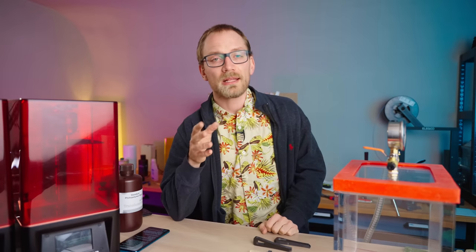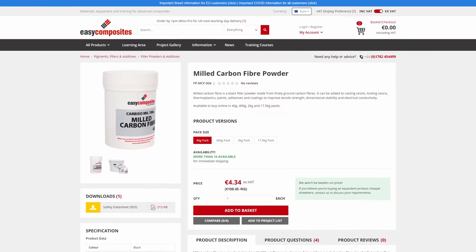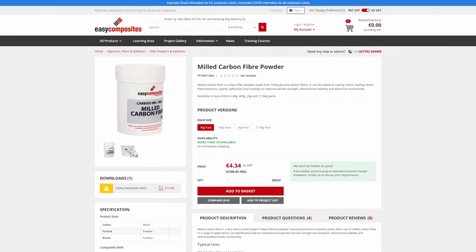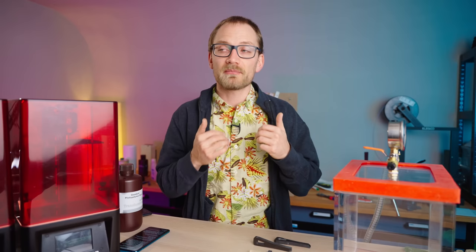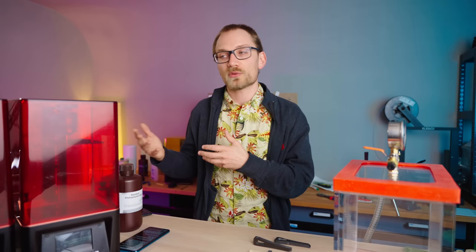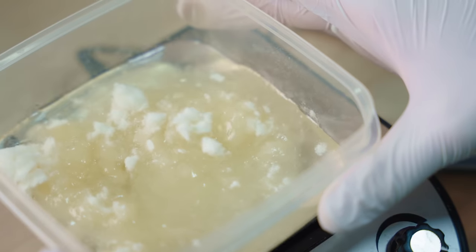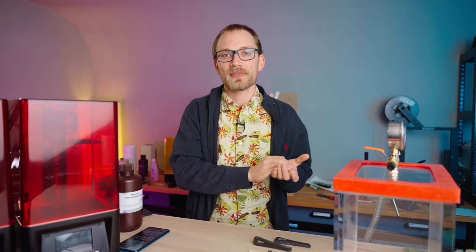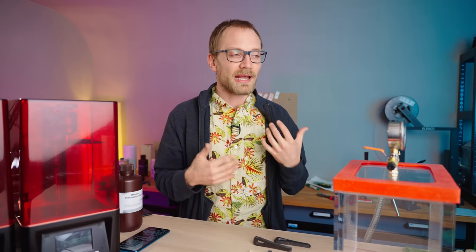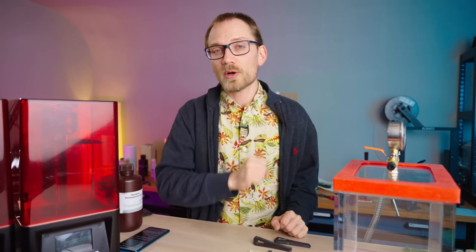In this case, I think there's also just not enough of the chopped fiber in the material to give an even improvement in strength, and if I would add more, it would not be very printable anymore. So what we're seeing is that there's just blotches of very strong and rigid bits in the material where there's the fiber added in, and then right next to it there's bits where there's no fiber in it at all, and that just creates a huge stress concentration right there. But that has me thinking. One of the potential materials that could still be tested is milled carbon fiber, which is a really fine carbon fiber powder almost. Would this actually be able to make the strength of these materials any better at all, or would we have to add in so much of that milled carbon fiber to a point where the resin slush that we're trying to print with is not going to be usable in the printer anymore?